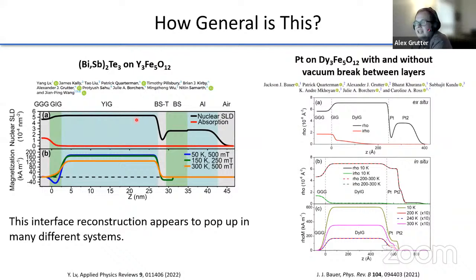Where growing yttrium iron garnet and then bismuth antimony telluride again gives you this transitional growth region. And it also appears, again, in a collaboration with here the Ross group at MIT, led by Jackson Bauer and Patrick Quarterman. What we found is that it seems like it may be related to having a vacuum break between the growth of your layers.